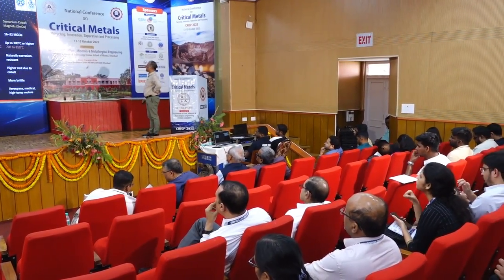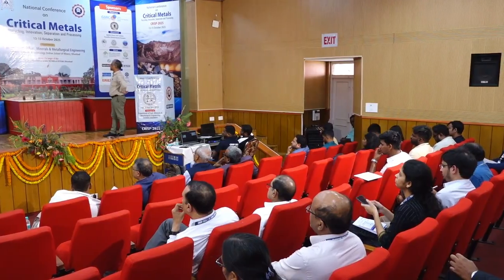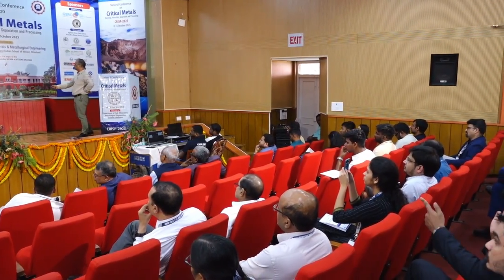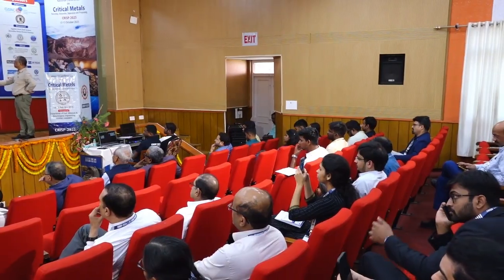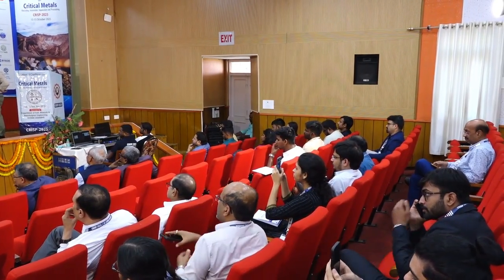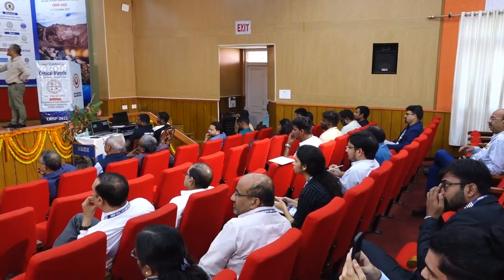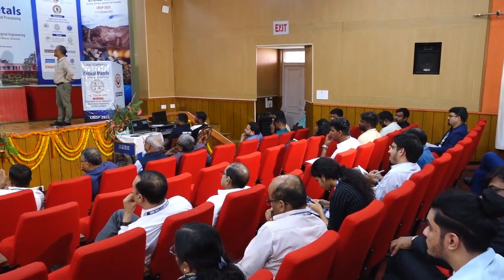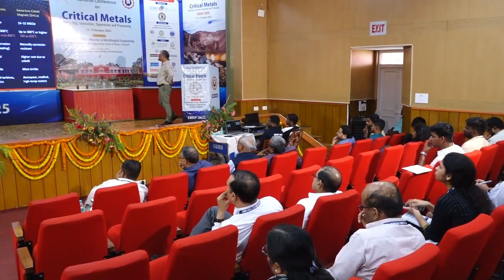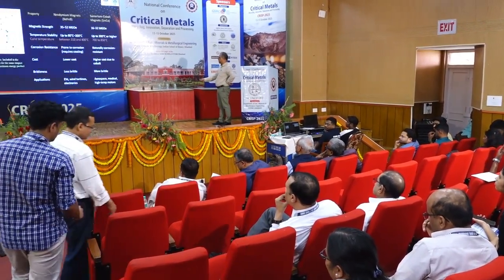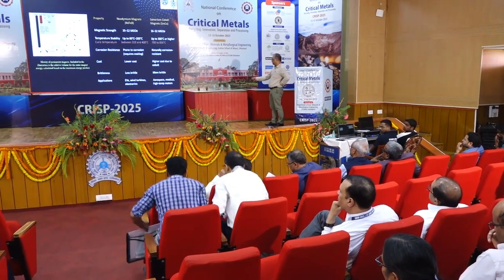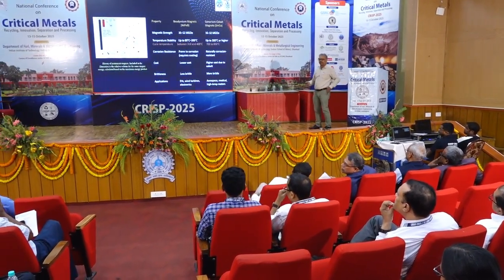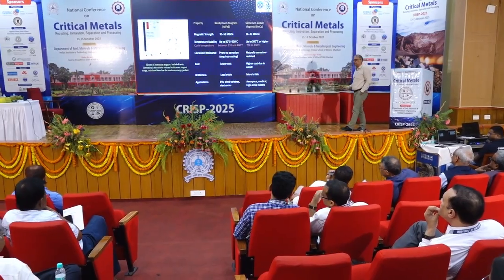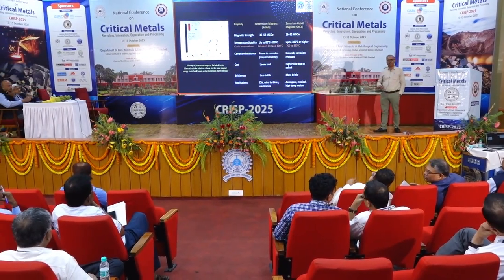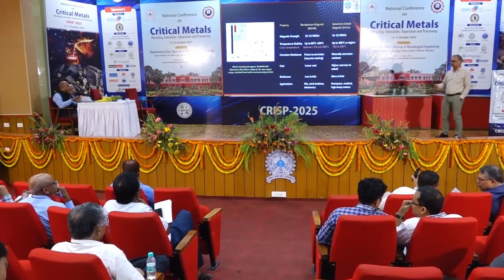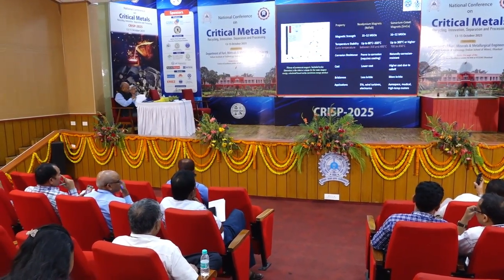So in a nutshell, this is the comparison between neodymium magnets and samarium magnets. When you talk about high temperature, it can go a little higher, and the Curie temperature is also mentioned here, which is a little lower compared to that, but it can go up to that level itself. The magnetic strength is 35 to 52, and this magnet has 16 to 32. Another effect is the handling of the magnet. This one is less brittle and this one is more brittle. Handling of magnets is also important, because ultimately it will go to the automotive grade, so it has to be handled by the workshop people working in the assembly line.